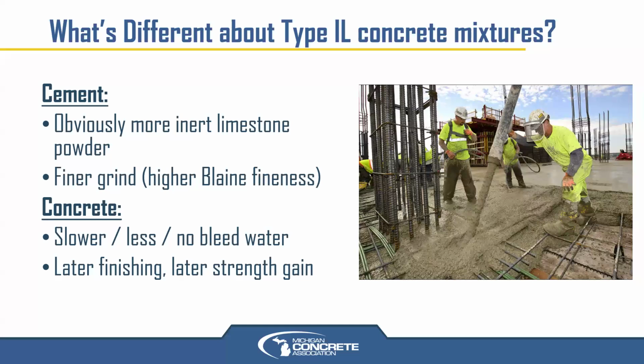Also, limestone is slightly softer than clinker, so the limestone particles themselves are typically ground a little finer. If you were able to identify each individual cement particle in that powder and classify it as limestone or clinker or gypsum and so on, generally the particle size of limestone is a lot finer than the average or typical particle size for the clinker, the actual Portland cement portion of it. So it's what they call preferentially ground, limestone in a mill at a cement plant. A lot of the fineness comes from the limestone, but the cement is finer too. What does that do to concrete?